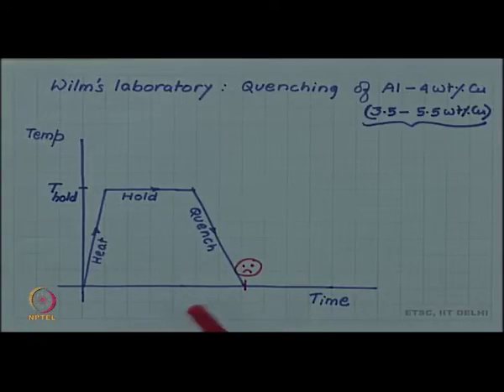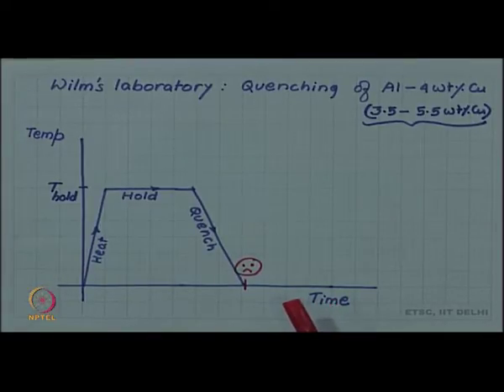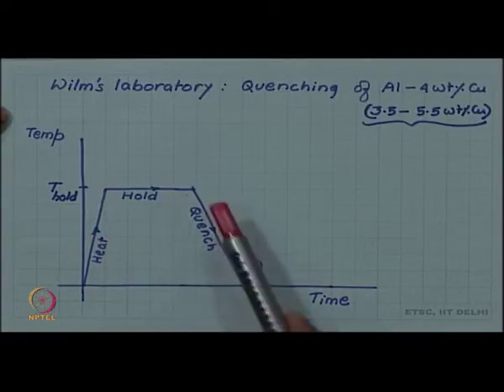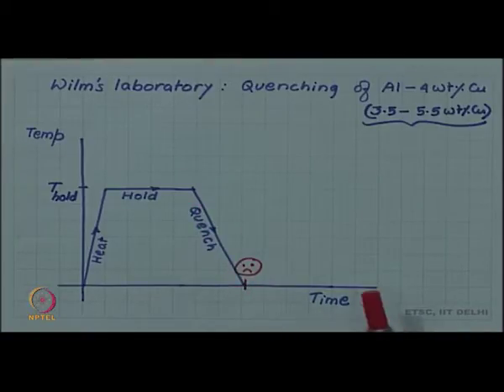On a Saturday morning, he decided to run the experiment again with some new variables, and he ran one set of experiment on this Saturday morning. But outdoors he found a beautiful sunshine, and he was a lover of sailing. So he heated, held and quenched, but before measuring the hardness, he decided to go out for sailing, have a nice sailing weekend. So he leaves for the weekend, he doesn't measure the hardness of the quenched specimen, goes for sailing and comes back on Monday morning to resume his experiment.